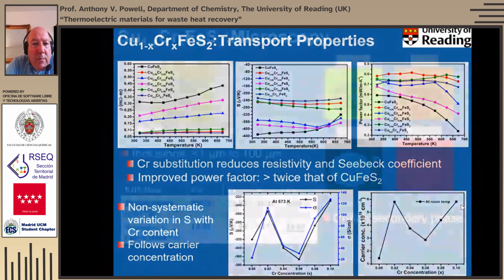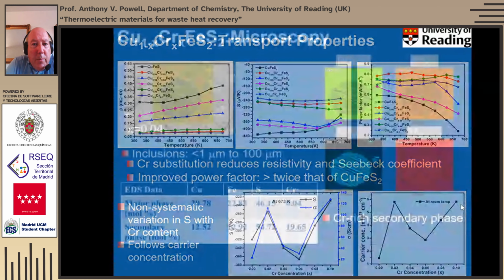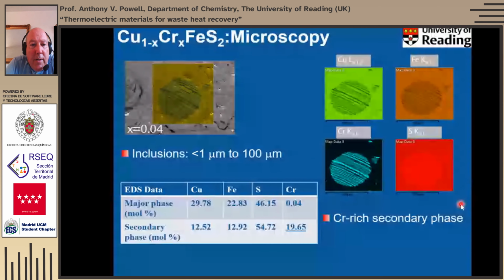So that really led us, with our colleagues at Manchester as part of the project, to look at the electron microscopy. And what we find is we find inclusions within these materials. This is just one composition here. This is 4% chromium. We find inclusions over quite a wide range of length scales, from the sub-micron level up to quite large inclusions like this one, which are almost 100 microns.